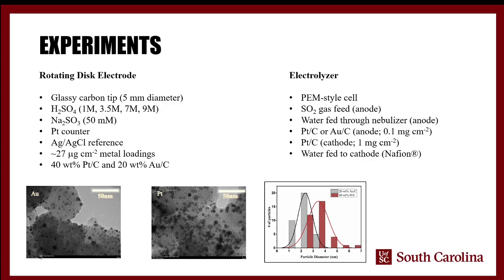If the Nafion gets too dry, conductivity tanks, and your cell resistance goes up dramatically, which means you have huge voltage losses across the cell, which means you need to put more voltage in to achieve the same current density. And so you have to manage your water very carefully.